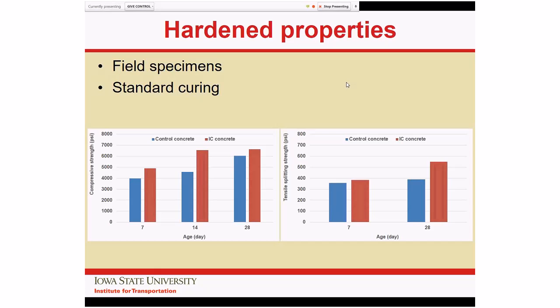So again, samples were taken from the mixture as it was delivered and tested in the lab. And what's interesting in this case is that the compressive and the tensile strengths were markedly higher with the internal curing, particularly at 28 days. And again, this is partially due to the increased slag content and due to the fact that the internal curing is indeed helping the hydration along.